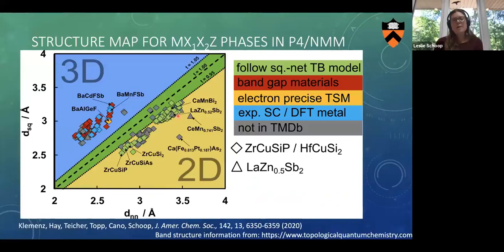And now the colors mean something different. We don't mean electron count. So now we compared our results with results which are published on this database here. You might know about this, which lists all the band structure and topological properties of materials listed in ICSD. And based on this band structure, we found this band structure motif resembling the square net tight binding model, and all these green points exclusively fall in the yellow area. The gray points are materials which are just not listed in this database. And then we find materials which have band gaps in the database exclusively in the blue area.